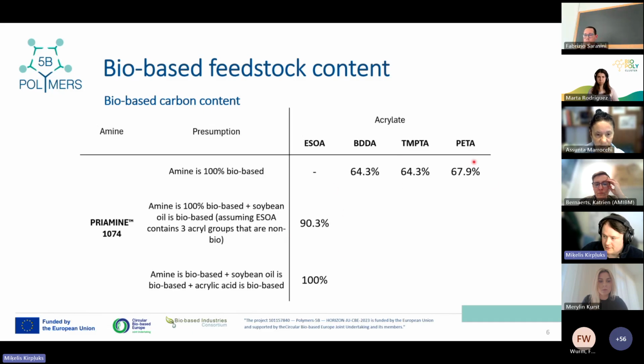And with other acrylates, there is relatively high biocarbon content in the resin if we compare to typical polyurethane materials. I come from the rigid polyurethane foam industry, and there you can obtain only about 20% bio-based carbon when you use biopolyols in the polyurethane development, if they are economically feasible.